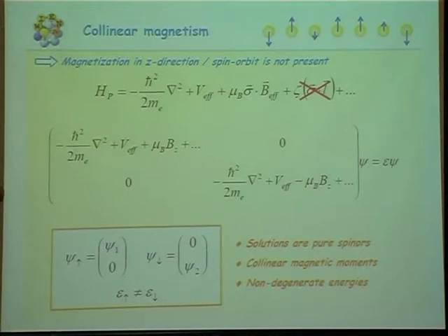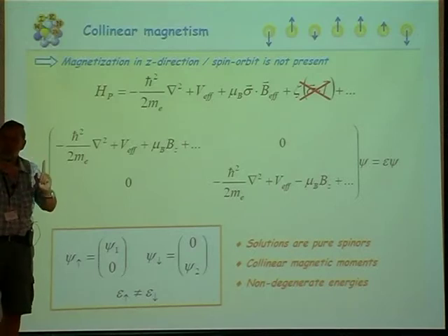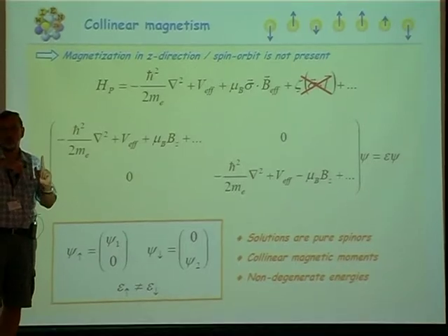We will do an antiferromagnetic calculation during the exercises where we have as an input already to specify that one vanadium atom should be spin up and the other vanadium atom should be spin down. Then we do the calculation, and if this antiferromagnetic alignment stays constant, then this is at least a metastable solution.